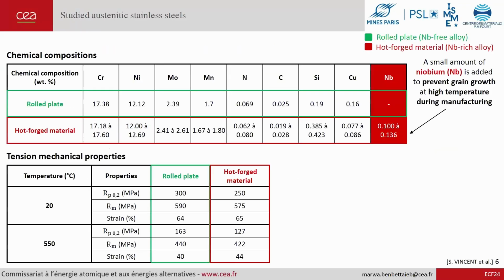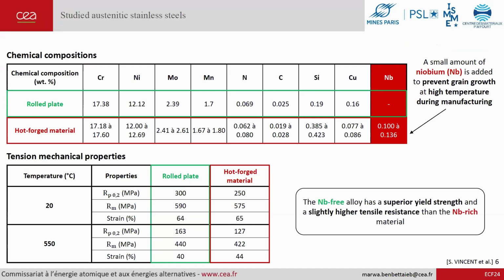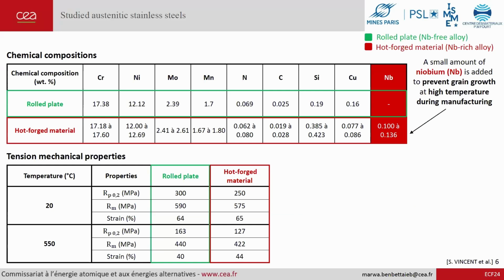Let's take a look at the properties of our stainless steel. So here we have two 316LN stainless steels that have approximately the same chemical composition. But like I just mentioned, to the hot forged material we added a small amount of niobium to prevent the grain growth during the hot manufacturing route. Please keep in mind this color code for the rest of the presentation. So the niobium-free alloy is presented in green, and the niobium-rich material is always presented in red color.